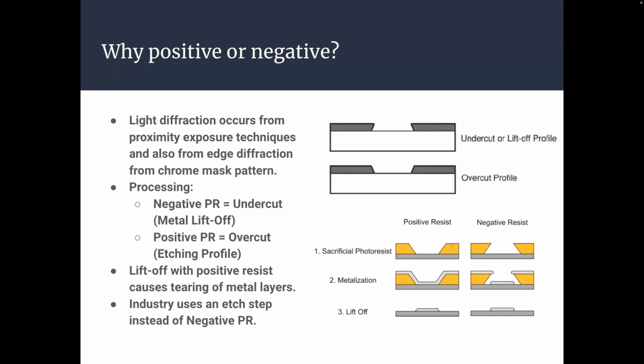Due to this, we don't get perfect straight vertical patterns in our resist. We actually get these trapezoidal shapes. The negative photoresist itself leads to an undercut. You can see it there, that upside down trapezoid, while the positive gives us an overcut, that kind of concave shape. These serve specific reasons, and we use them for very specific purposes. For positive, we use it for an etching profile, since we get the smaller, more resolved feature at our substrate surface, so we end up using that for etching.